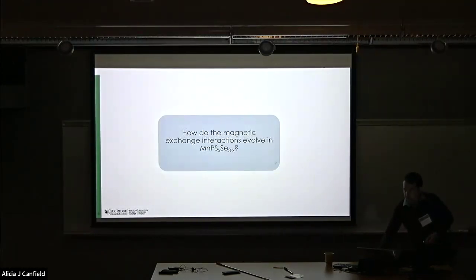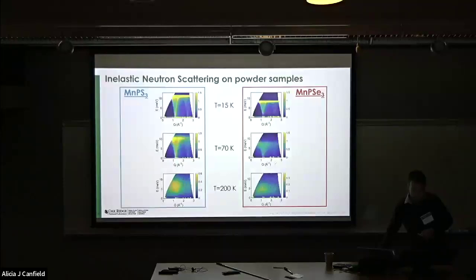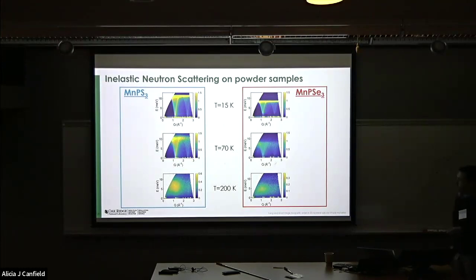I guess I've got 5 minutes, so in the next 5 minutes I'll talk about the exchange interactions, to try and round out the story. We performed some inelastic neutron scattering measurements on both materials, S3 and Se3. This is the temperature series where you can see well-defined correlations at low temperature. Just below the transition you can still see spin waves, and even at 200 Kelvin you see some correlated features, although of course very broad.